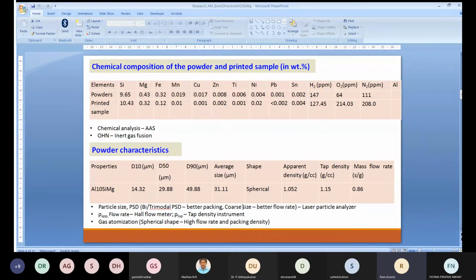Before printing the samples, for the powder we measured size, shape, apparent density, tap density, and flow rate. Particle size and particle size distribution we measured through a laser particle analyzer. Sieve analysis could not be used for particles less than 40 micrometers in general, which is why we went for the laser particle analyzer. The idea here is we should have a bimodal particle size distribution for better packing, with more particles in the coarse size so that you have better flow rate. Apparent density and flow rate we measured through a Hall flow meter, and we have a tap density instrument,